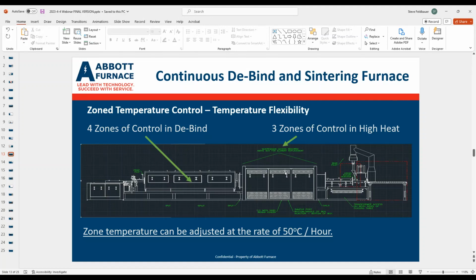In the case of a continuous furnace, all we need is to wait. If we want to change the high temperature zone, change that setup, all we do is wait till the parts exit into that neck on the right-hand side of the hot box. And at that point, we can start changing the temperatures because our last boat would be in the cooling section. We could already have loaded parts into our debind. We could be going through our debind, and our temperature can be changed at 50 degrees C per hour. Okay. And you're going to push a plate about every 20 to 45 minutes, depending on your cycle.